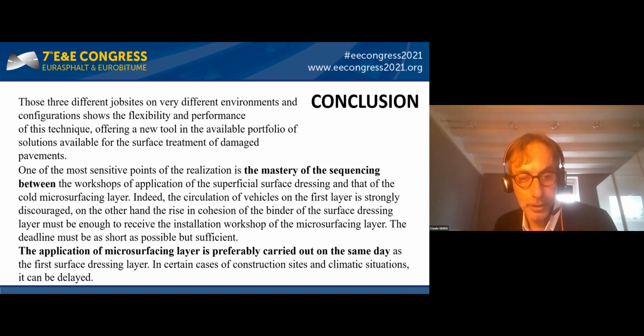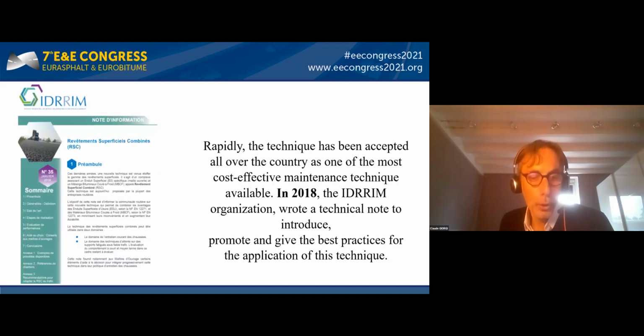One of the most sensitive points of the realization, though, is the mastery of the sequencing between the workshop of application of the surface dressing and the one of the cold microsurfacing layer. Indeed, circulation of vehicles on the first layer is strongly discouraged. On the other hand, the rise in cohesion of the binder of the surface dressing layer must be enough to receive the installation workshop of the microsurfacing layer. The delay must be as short as possible, but sufficient. Rapidly, this technique has been accepted all over the country as one of the most cost-effective maintenance techniques available.